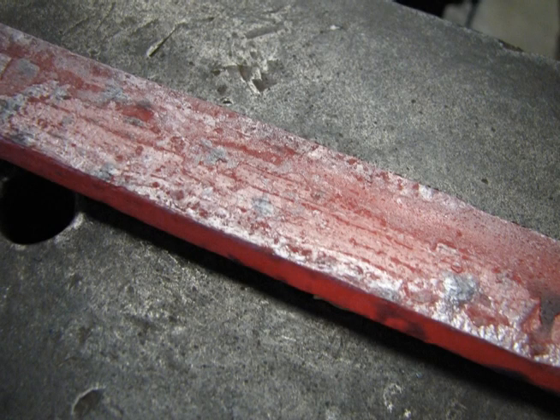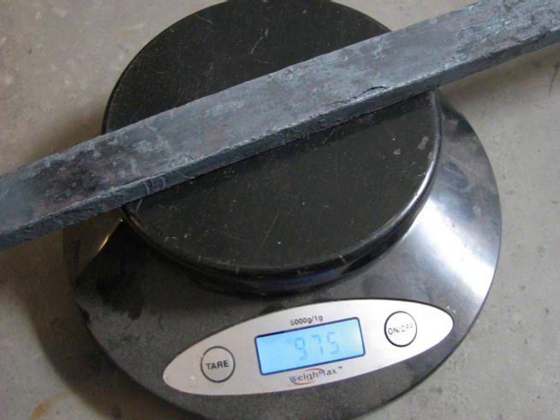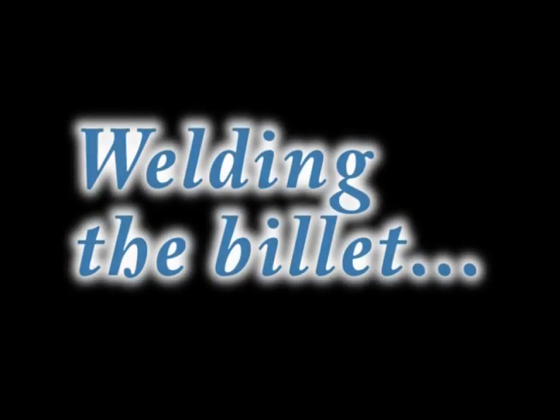The pattern of layers is visible to the naked eye. This bar used to be 1.4 kilograms and now is about 1 kilogram. That's a 30% loss to become the edge bar after having lost 20% in going from bloom to bar. So now it's time to put the billet together from the different bars.